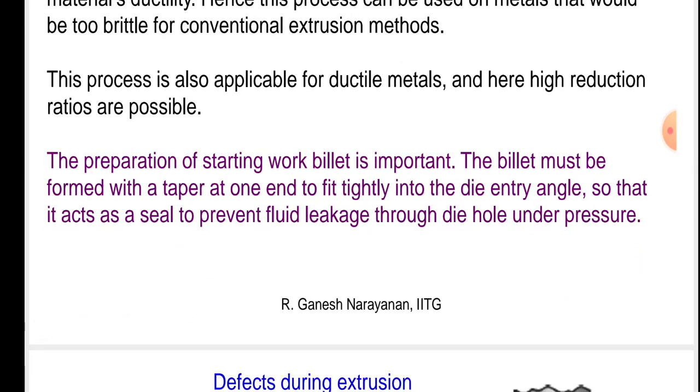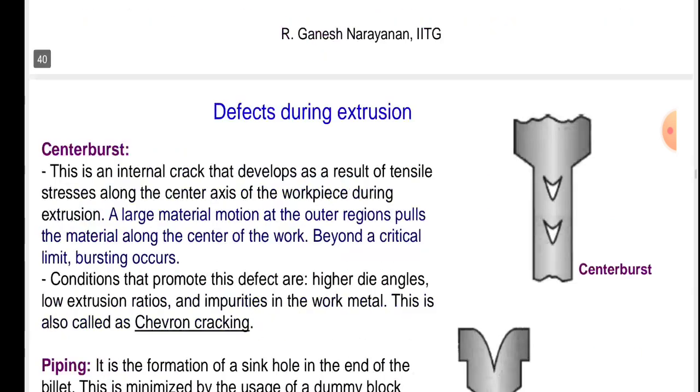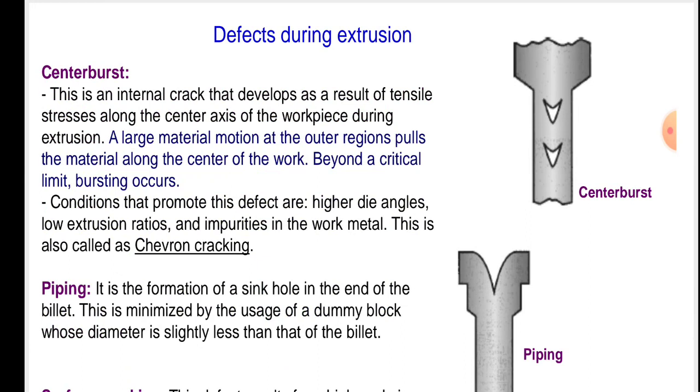The preparation of starting work billet is important. The billet must be formed with a taper at one end to fit tightly into the die entry angle so that it acts as a seal to prevent fluid leakage through the die hole under pressure.